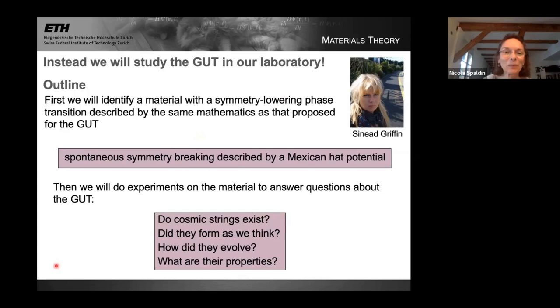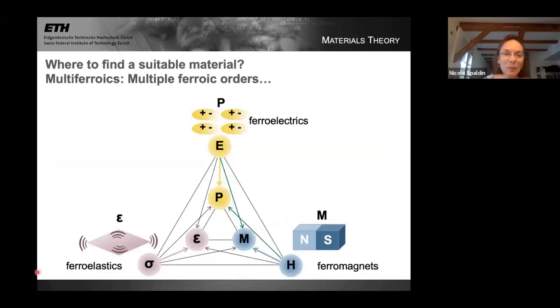Thank you. Okay. So where to look for a suitable material? We want a material that has a spontaneous symmetry lowering phase transition described by a Mexican hat potential. And the place that we decided to look was in the class of materials called multiferroics, which are materials that have multiple ferroic orders simultaneously in the same phase. So they have, for example, a spontaneous electric polarization. They have electric dipole moments that are switchable by an electric field. This is what we were looking at the very start in the piezo force microscopy image, a map of these electric dipoles. They have a spontaneous magnetization that's switchable by a magnetic field, like the cartoon example that we looked at earlier, and a spontaneous deformation that's switchable by an applied stress. And they have combinations of these together.